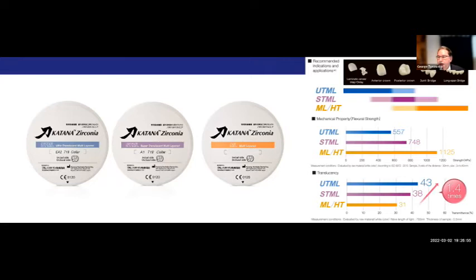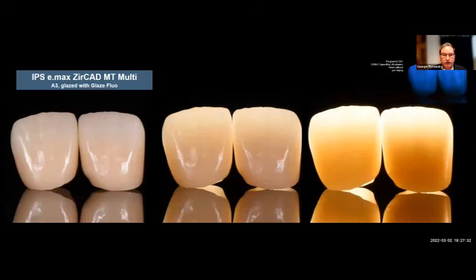So again, showing you some of the strengths we talked about as far as translucency. The 5Ys and the 4Ys have the most translucency. And if you look at this profile here, it's very clear. You go from a 3Y, the MLHT at 1125, the STML, which is a 4Y, at 748, and the UTMLs drop to about 557. And in an inverse relationship, again, the higher the strength, the higher the density of the crystal structures, they're more opaque, to more translucent with the other materials. So again, clinical judgment is related to the need of the final restoration.